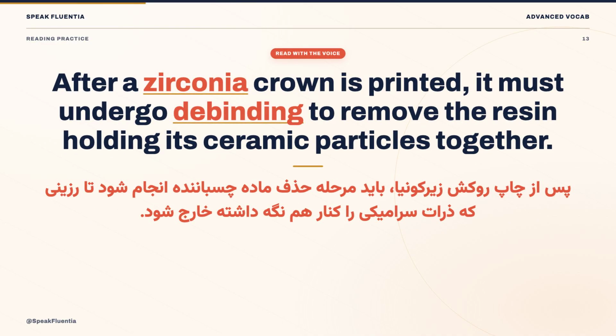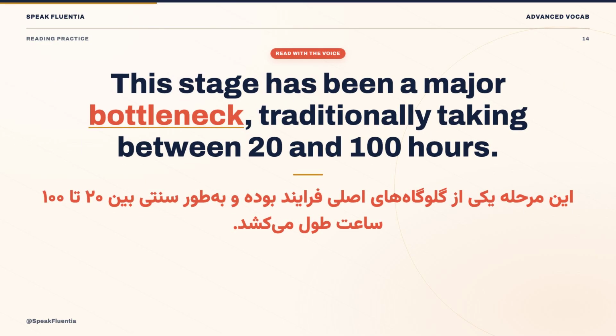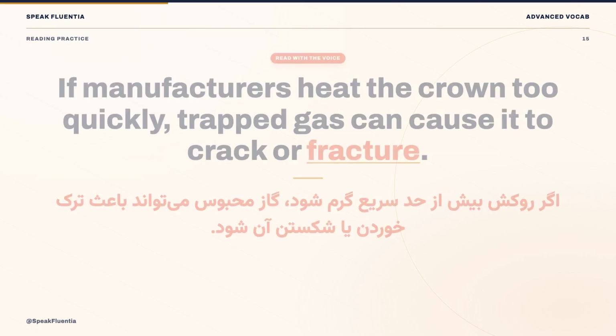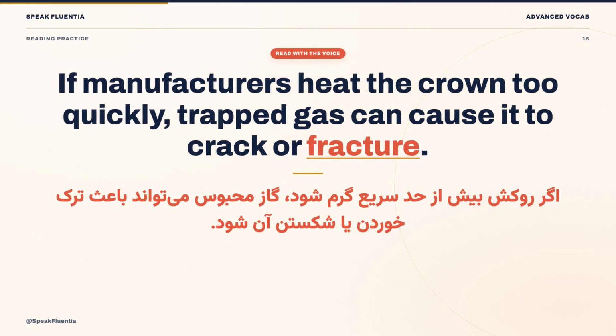After a zirconia crown is printed, it must undergo debinding to remove the resin holding its ceramic particles together. This stage has been a major bottleneck, traditionally taking between 20 and 100 hours. If manufacturers heat the crown too quickly, trapped gas can cause it to crack or fracture.